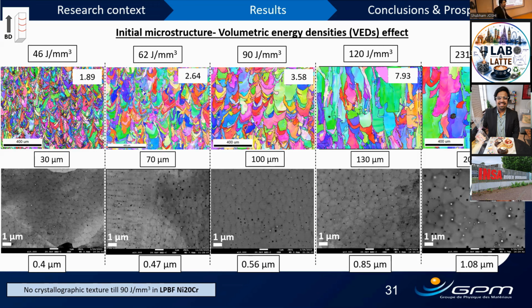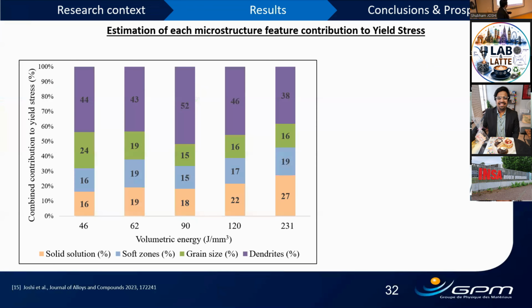So apart from these values, we can actually use the same model that we used in the previous 62 joules per millimeter cube modeling. By computing, I wanted to show a table with all the values, but it was too much data. So directly, let's move on to the graph. What we see here is again the influence of solid solution at the bottom, the dislocation density in soft zones contribution, grain size contribution, and finally dendrites. For all the volumetric energy densities, we can see that dendrites again have the highest contribution. So irrespective of what process parameter you choose, at least in the range that we have selected by our model, these cellular dendritic structures are most influential.